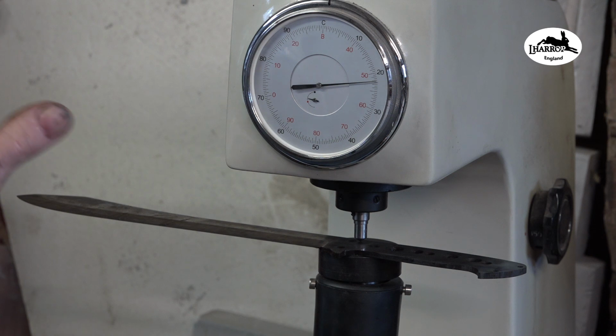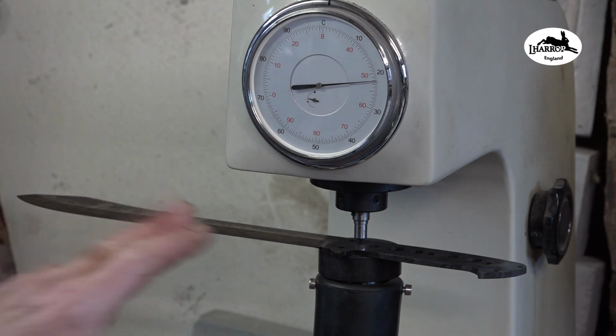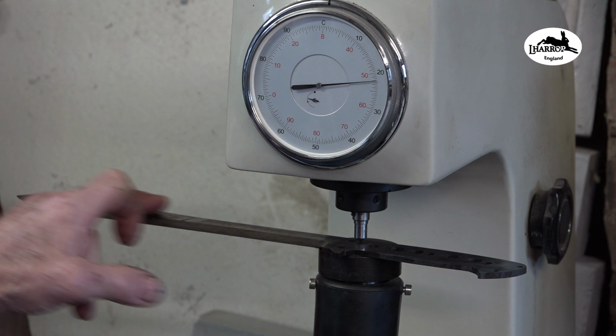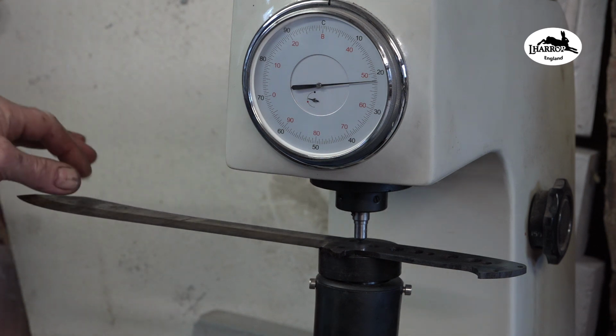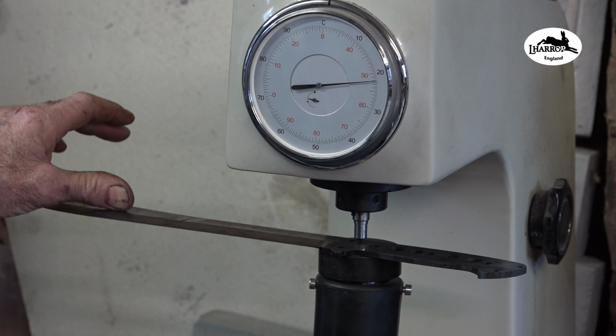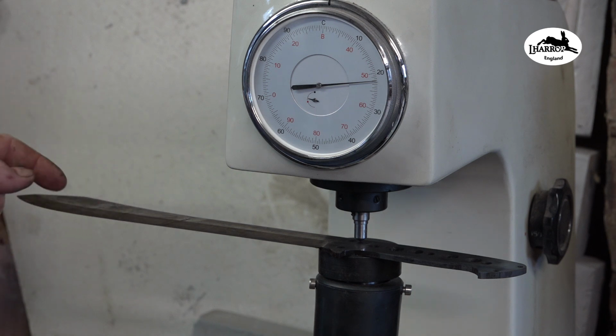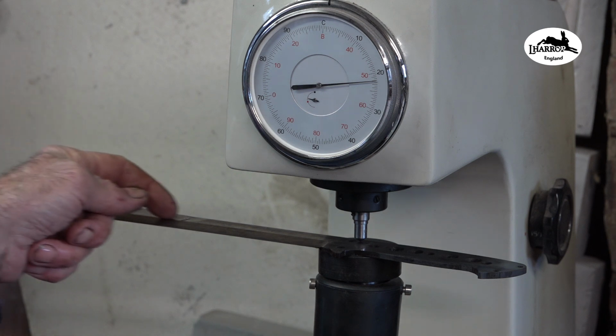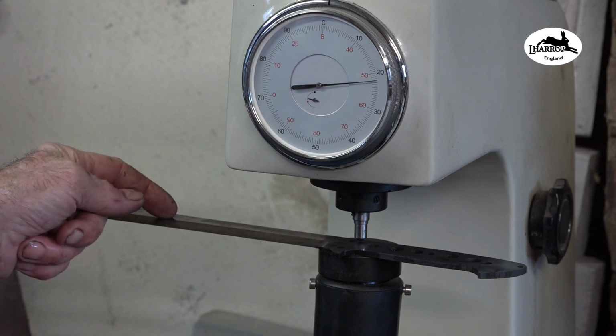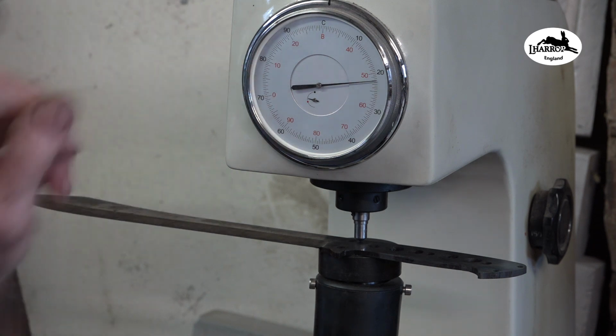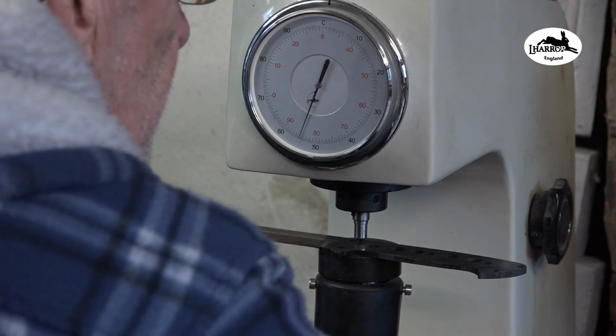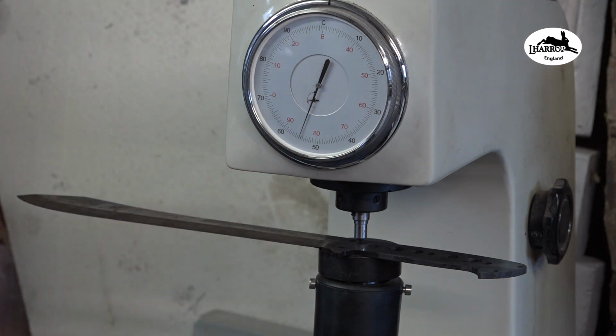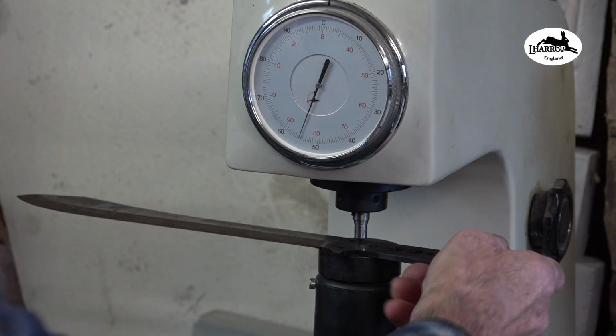The tempering temperature of the core steel is an awful lot lower than the tempering temperature of the Damascus, the 1095 and the 15N20. So the only way I can reduce the hardness of this blade was to blue back the spine, which will run the heat down almost to the bevel. So at the edge of the bevel, I reckon the Damascus there will probably be around 59 to 60. The jacket should be about 55. The jacket is 55. That's absolutely perfect.